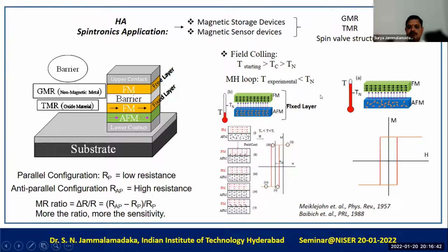Once we cool the sample through the Néel temperature of the antiferromagnetic material through the field cooling process, the spins of the ferromagnetic material will be pinned at the interface due to the antiferromagnetic interface. Due to this pinning, when we measure the magnetic field versus magnetization graph, one needs to apply a larger magnetic field to reverse the magnetization. As a result, there will be a shift of the hysteresis loop along the magnetic field axis. This shift is called the exchange bias. This exchange bias phenomenon has been used in many devices, TMR devices, and also in spin valve structures.